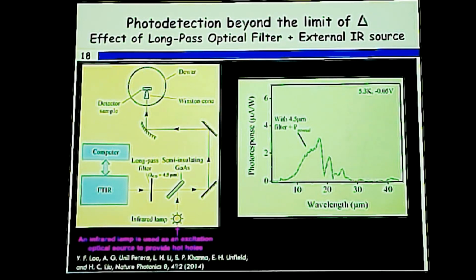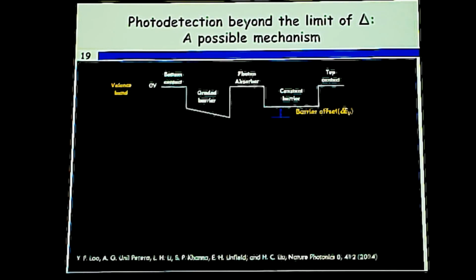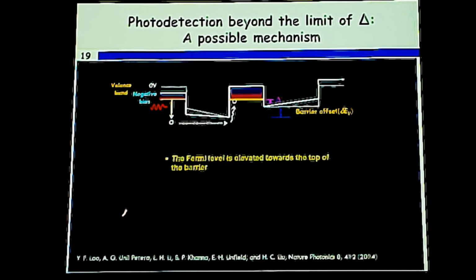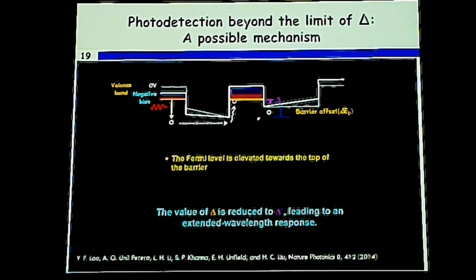And based on the results, one possible mechanism of this photodetection was suggested. In this one, the high energy injected carriers from the bottom contact were supposed to redistribute their energy so that the Fermi level is elevated, and now infrared radiation with smaller energy can be detected. So that was the suggestion.